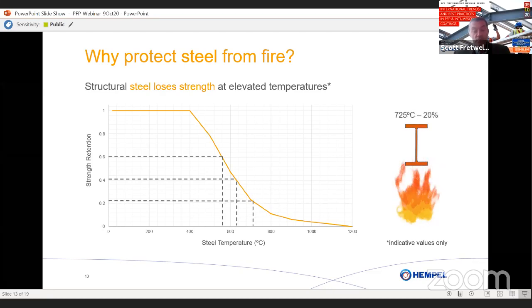And if we continue that rate of steel temperature increase to 725 degrees C, it's now lost almost all its strength. It's lost 80% of its strength. And depending on the load being applied to the steelwork, you can see at some point that this steel profile will not be able to support the applied load, and then we have the serious possibility of structural failure.